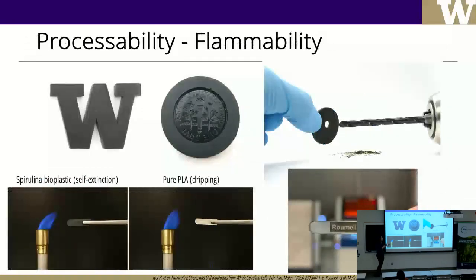You can compression mold or transfer mold, or you can do machining, or you can do laser cutting with those. So we are demonstrating that you can actually use that as a regular plastic. One of the good things, of course, when you're using biomass and charring biomass in this particular case is that it will have self-extinguishing properties. So when you take it out of the horizontal flammability test, it will self-extinguish, it will stop the flames.